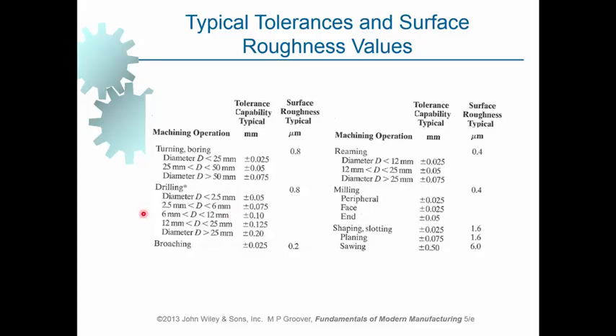What happens is that once we make the hole by making use of the drilling machine, we cannot achieve the required tolerance. So we may need to introduce an additional reaming operation, this one, providing us with the possibility of achieving the assigned value of the tolerance, that is 0.025. So we need to make the hole first and then apply a reamer on top of that in order to enhance the precision of the drilled hole. Or if for the same hole we assign a surface roughness of 0.4, then it cannot be achieved in the drilling process, and we may need to apply a reamer after drilling in order to improve its surface roughness, indeed to improve the surface finish,